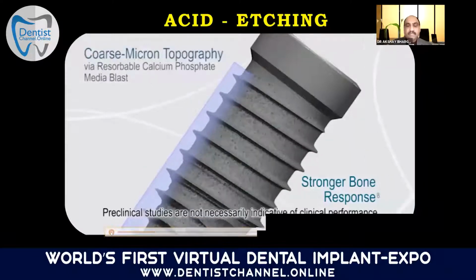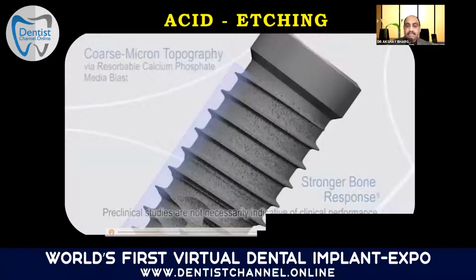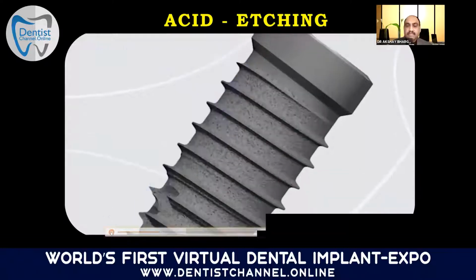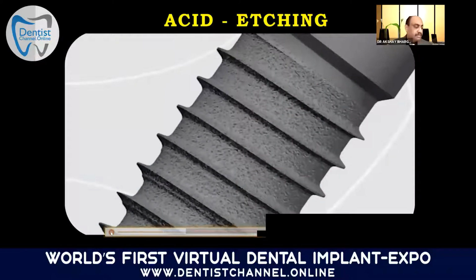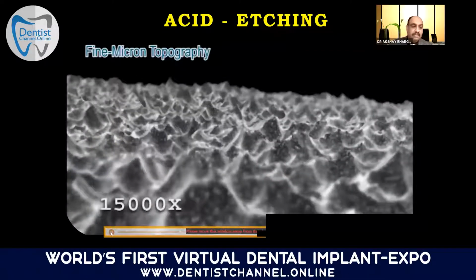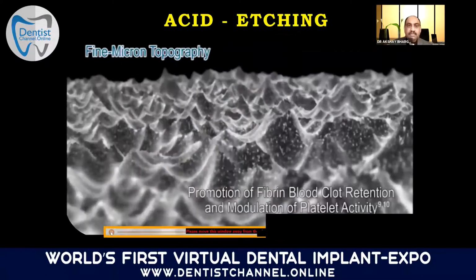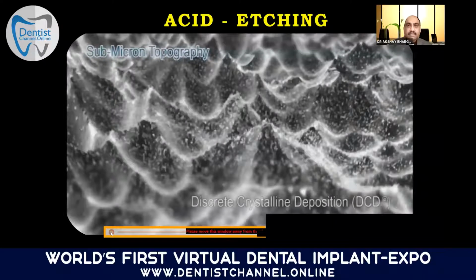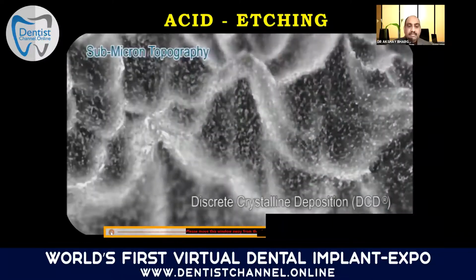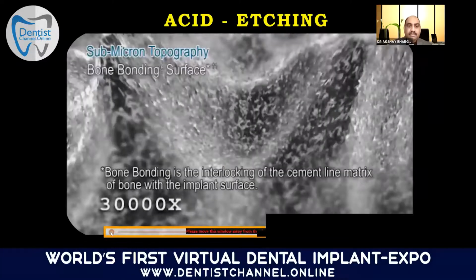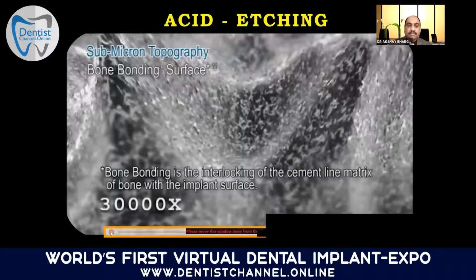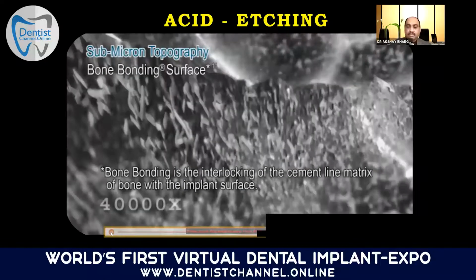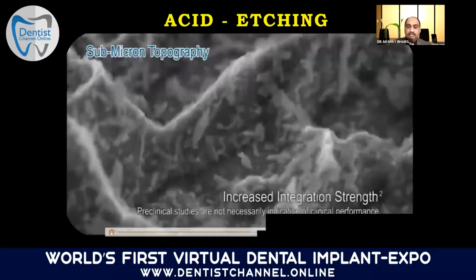Dual acid-etched micron topography features have been shown to support osteoconduction mechanisms, including the promotion of fibrin blood clot retention and modulation of platelet activity. The discrete crystalline deposition of calcium phosphate nanoparticles establishes a bone bonding surface. In a preclinical study, the Biomet 3i T3 implant with the DCD surface demonstrated increased integration strength throughout the healing phase compared to less complex surface topographies.